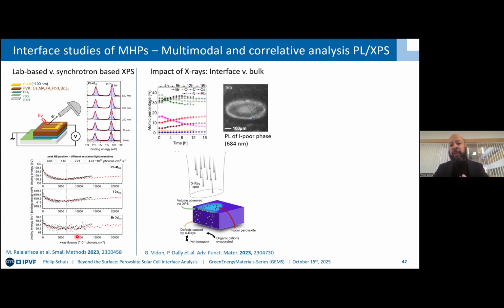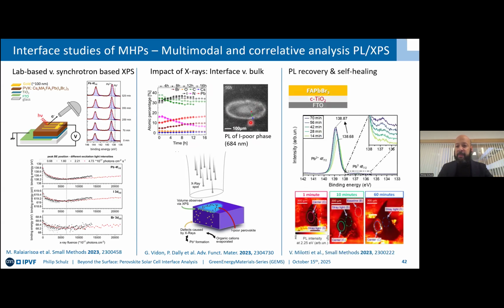You can, however, also couple this to very targeted degradation experiments. So here, again, just an XPS measurement of our triple cation mixed halide. You can, of course, then see in the spot change of the different core levels, a decrease in iodine and nitrogen. And indeed, when you do the photoluminescence imaging, you get a true metric of the optoelectronic changes induced in this iodine-poor phase.